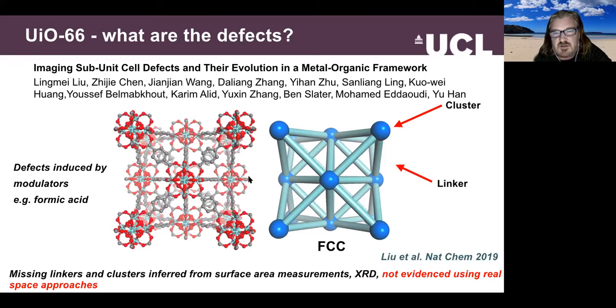catalyst. And it's been established for quite some time that the efficiency of the catalyst is proportional to the concentration of defects within this material. And it turns out you can prepare this material with 40% of defects, which is really extraordinarily high. The issue is, what's the proportion of cluster versus linker defects?